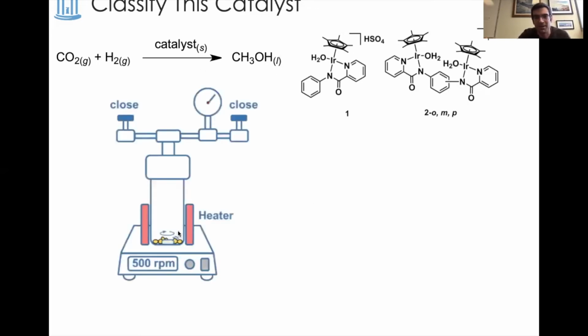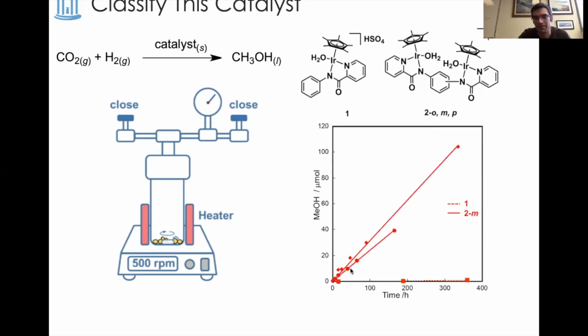So the reactor looks like this. It's a pressure vessel, solid catalyst stirred with CO2 and hydrogen gas. And they looked at this monomeric iridium complex as its solid powder, as well as this dinuclear complex as its solid powder. And what they observed is that the dinuclear catalyst in the solid lines produces a fair amount of methanol, certainly relatively speaking to the monometallic catalyst, which is essentially inactive. And this reaction is more efficient in this gas phase setup than it is in a homogeneous solution.